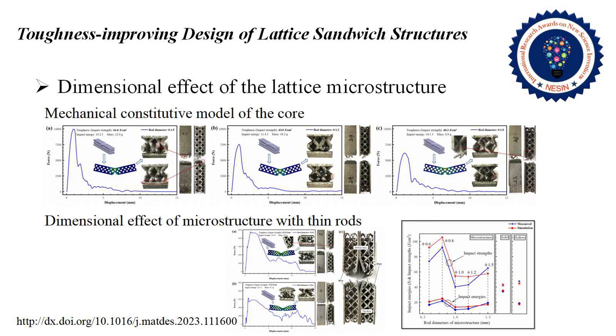It propagates along the direction of maximum shear stress. In addition, the compressive stress in the top skin can inhibit the formation and propagation of cracks, resulting in this area rupturing last. And the lattice structure samples also form discontinuous cracks. Thus, the components continually repeated the process of initiation and propagation of cracks. Because the energy expenditure of crack initiation is higher than that of crack propagation, cores with lattice structures can improve the impact toughness of components.